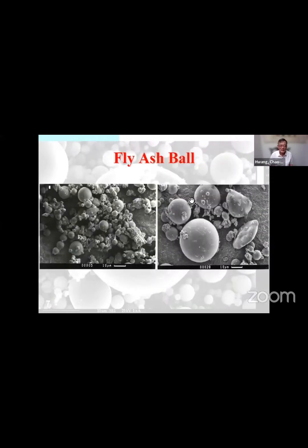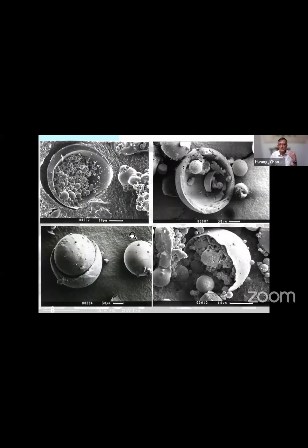You look at the size here, 10 microns. The size can be 30 microns down to 1 or 2 microns. Some particles are very, very small. The small particles of fly ash can be used as a fire resistant material. In Taiwan it is used for high insulation materials. The big spherical balls actually contain a lot of different sizes of fly ash particles. After you grind them, they can release a lot of very useful fly ash particles, which aid in reducing the cement required.